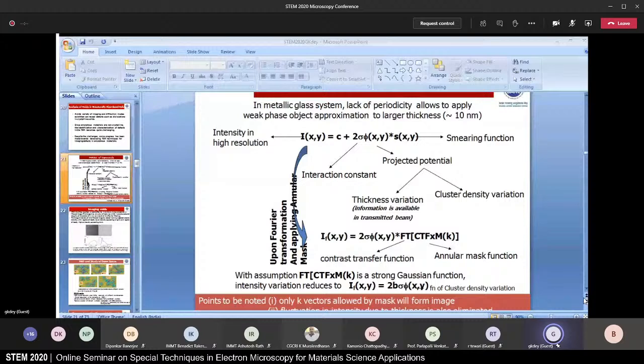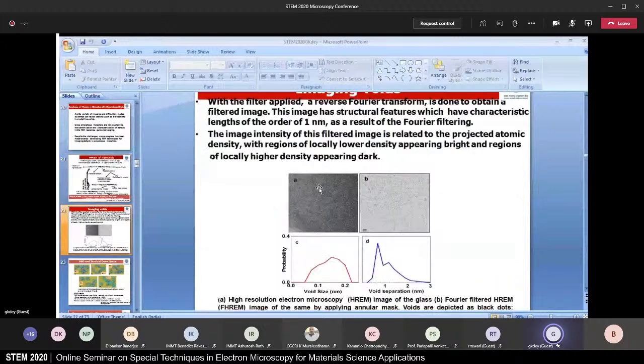This is the high resolution image of the glass, and if you do reverse Fourier transform, you will get an image like this, where you have dots which actually represent the open space inside the glassy structure, and the white space actually represents the regions where we have medium range order and short range order. So if you see these black dots, they actually are the voids present in the structure of the glass.